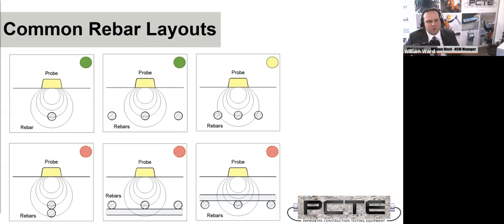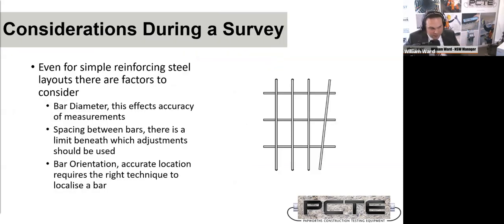The other source is, of course, keep away from perpendicular bars, whether they're above or below the bars to which you're measuring. You want to be, as much as possible, isolating a single bar. Now, a couple of other considerations is, do try and work out orientation. So you don't really want to only do one longitudinal and one perpendicular scan. It's not quite enough information.